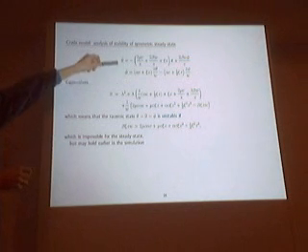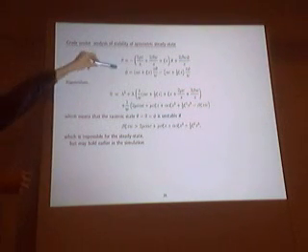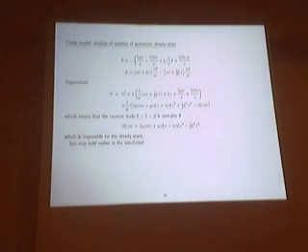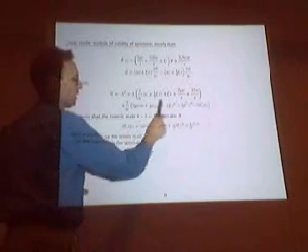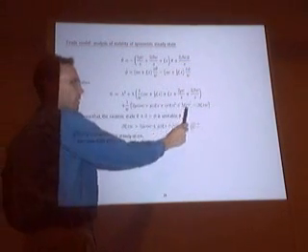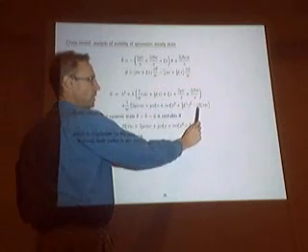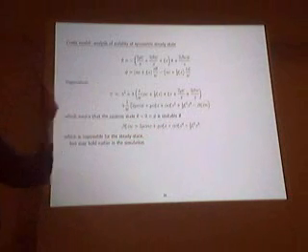It's the theta and the phi equations you need to worry about if you want to know, can you get a chiral solution, and is it stable or not? And the condition for stability comes down to the eigenvalues of the system. For stability, you just work out basically the determinant of this system, which is this term at the bottom, and you need the determinant to be negative in order to give you instability. And since we're dealing with concentrations, we know all of these terms are positive, and we've got a plus here, plus here, plus here, plus here. This is our only hope of having an instability. Only hope is that this term would be bigger than all of those 4 put together.